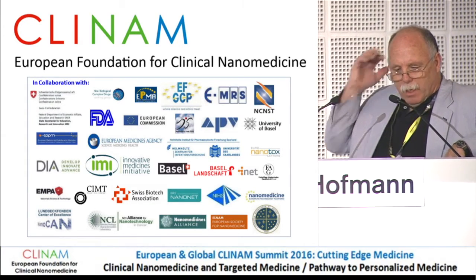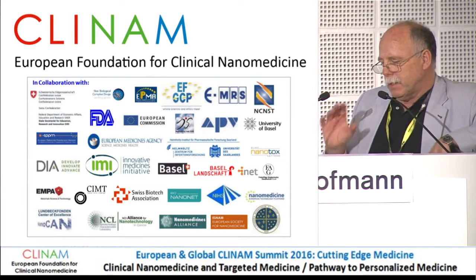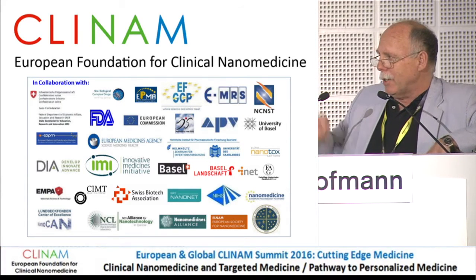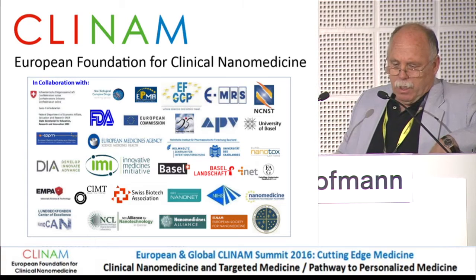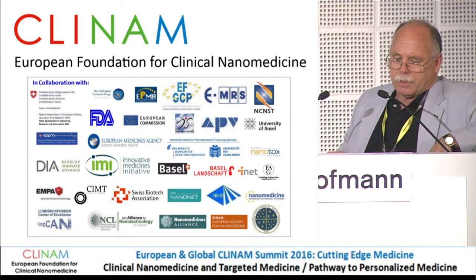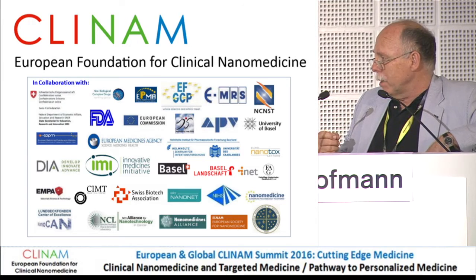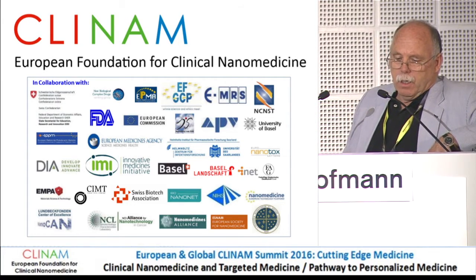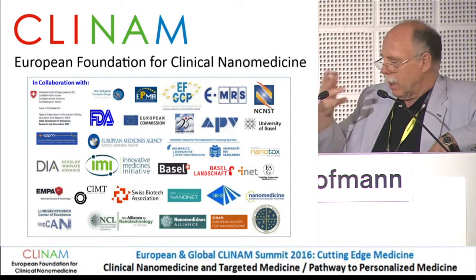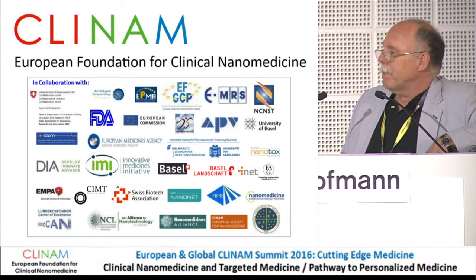Yes, we have different methods. If you go for direct organic coating, functionalization means first we need a first layer, which makes the whole thing biocompatible and colloidally stable, because iron oxide has an isoelectric point at 7, so the particles aggregate in the blood. So we have to stabilize this. This we can do with phosphate groups, for example, which bind relatively well to the particle. Then we need further functionalization to bind the aptamers and antibodies to the particle.